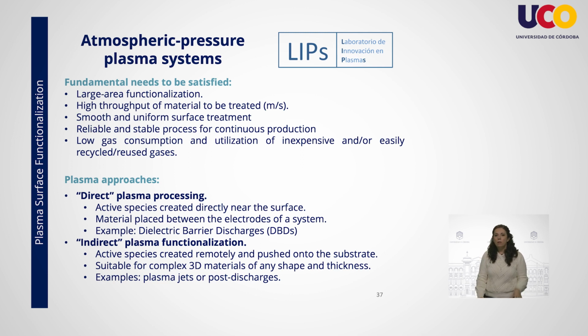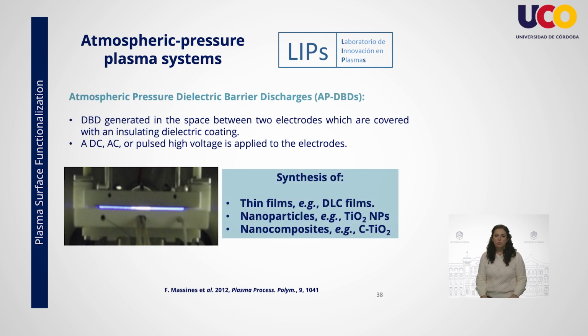Next, we will revisit both the dielectric barrier discharge and post-discharge processing of surfaces for different surface functionalization. As has been discussed previously in this lecture, and making a very rough generalization of the system, we could mention that atmospheric pressure dielectric barrier discharges are generated in the space between two electrodes, each of which is covered by an insulating dielectric coating. A substrate can be placed in between both electrodes, and thin films, nanoparticles or nanocomposites can be deposited on it. Depending on the plasma parameters and precursor nature, new material properties can be tailored. In this lecture, let's focus our attention on its use for the synthesis of thin films such as diamond-like carbon, nanoparticles such as titanium dioxide nanoparticles, or nanocomposites.